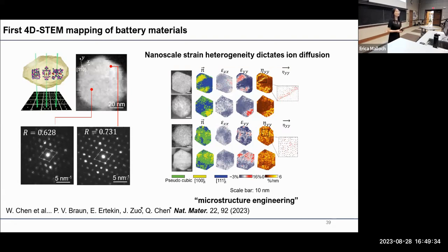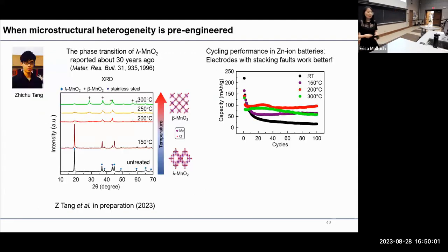With those maps, at this unprecedented nanometer spatial resolution, for the first time we're able to identify that the microstructure, the spatial distribution of phase domains, can actually impact the ion diffusivity by more than tenfold. This suggests that, in addition to composition, just changing the microstructure can also be very important for energy storage materials. In this example, we're using a single crystalline material to begin with, and the microstructure really formed after electrochemical cycling.